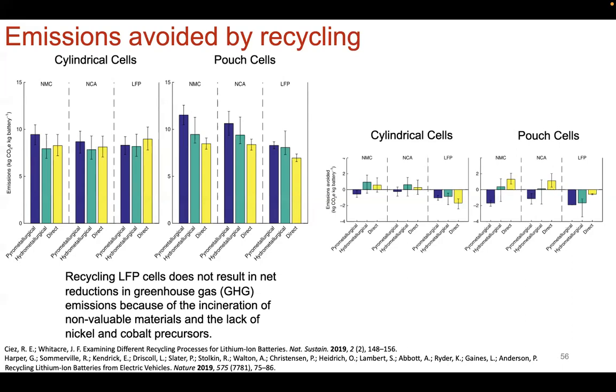Right. So let that sink in. Okay, based on this model, let that sink in. The amount of greenhouse gas emission is actually not avoided because you're spending so much energy and you're producing CO2 to burn and incinerate all the other stuff that's in your battery as well to try to recover the LFP active material. Okay, so these are the kind of quantitative metrics that we're aiming for when we talk about sustainability, and not make blanket statements like recycling is good.